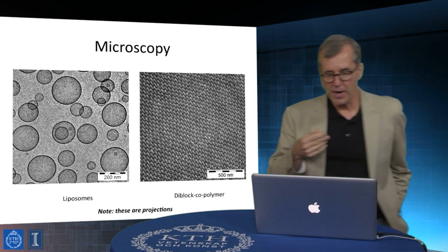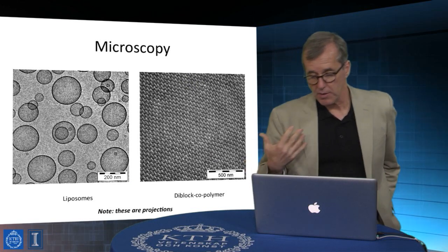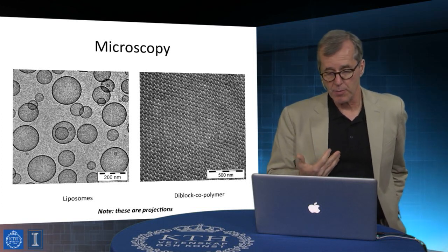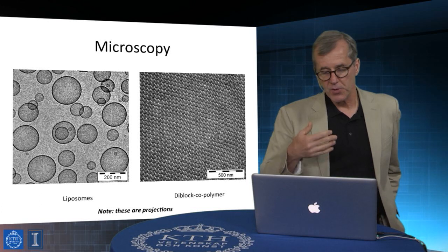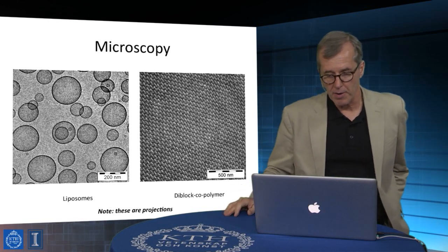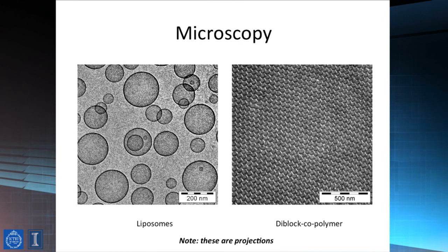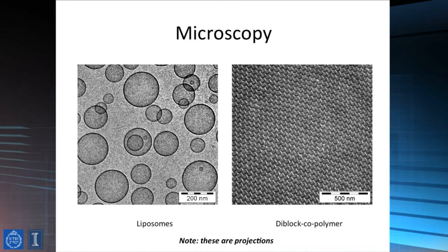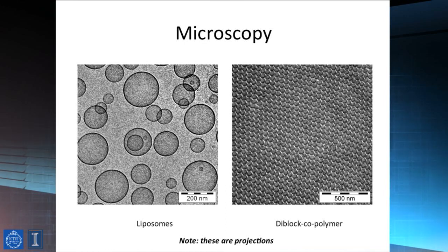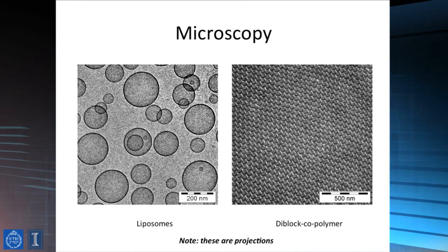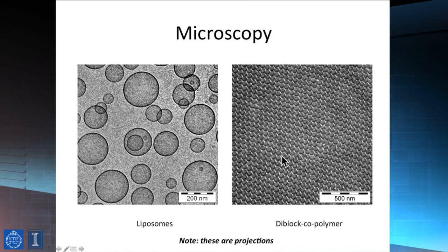Okay. And finally, microscopy figures very importantly in the characterization of polymers. Right. So I show, well, the first case is actually a polymeric liposome dispersed in a fluid phase, and you can see that that's a heterogeneous structure, right? But that's something that we can characterize via microscopy just by the kinds of phase contrasts that are possible. The second structure here is actually an ordered cylindrical phase in which one component's been physically removed, I believe in this case, of a diblock copolymer.